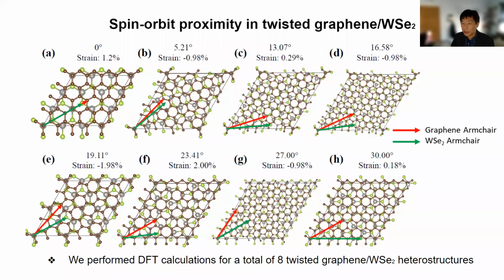You might be able to lock the graphene onto the TMD, because the strain is small, so it might be sufficiently lower than the sliding energy. But in most cases, in the experiment the strain will be much lower. In terms of calculation, though, we do have to incur some strain. Another way out of this is to choose a much larger unit cell, but that would make it very numerically expensive.